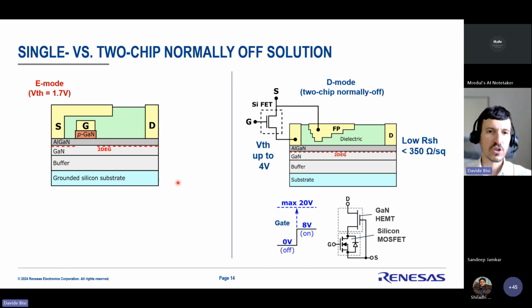The other architecture that's been successful in the industry, you can see on the left, is the so-called E-mode device, which is a single chip, normally off. To do that, the first thing is engineers have to reduce the charge density in the channel, so resistance actually goes up. The resistance of an E-mode chip can be 500 ohms per square or more, because there's a trade-off between threshold and resistance. If the charge is too high, the threshold will become negative. And then, of course, they have to have a p-type GaN under the gate to deplete charge under the gate and have a normally off device. So threshold voltage is 1.7 volts, which is barely enough to keep it off, but enough to be successful in the market.